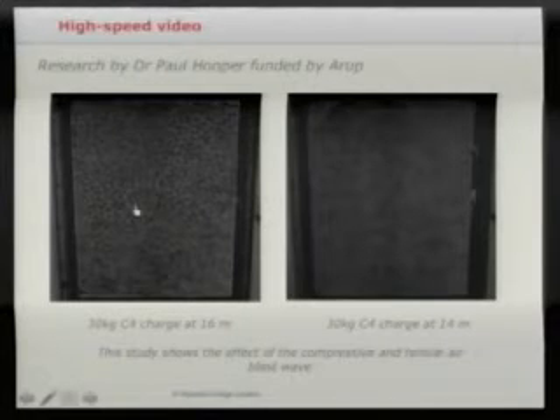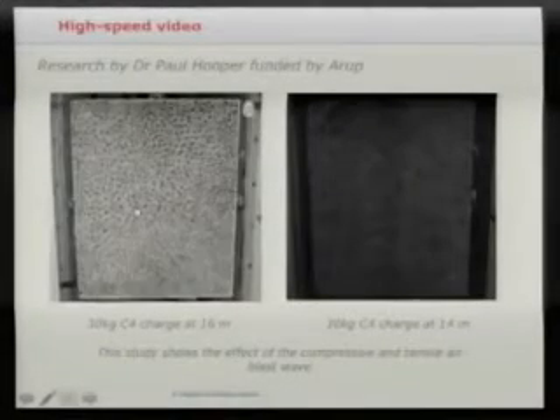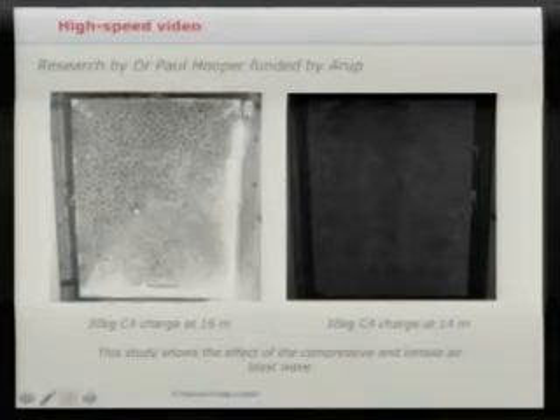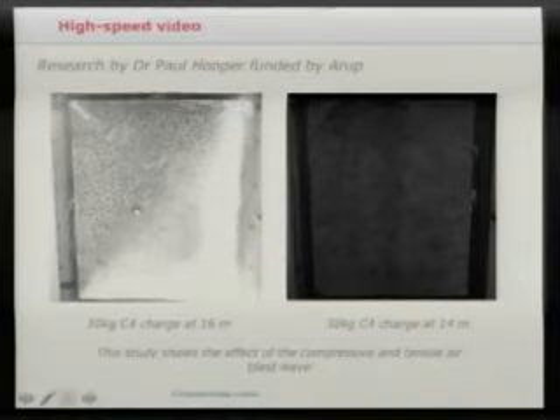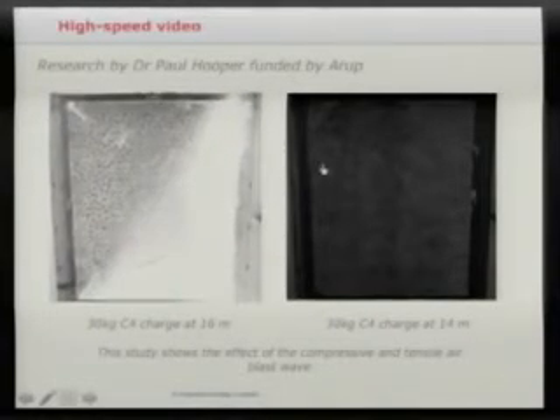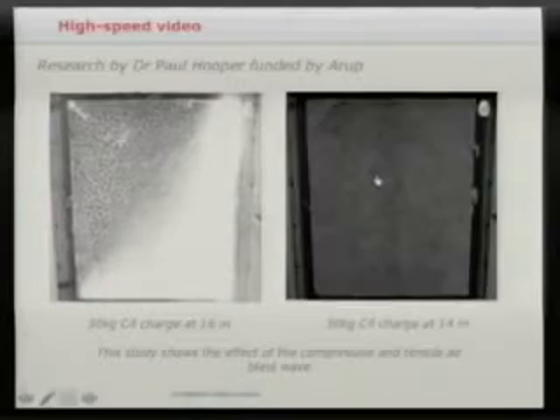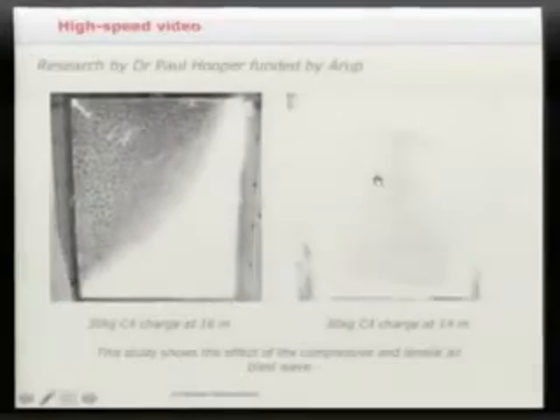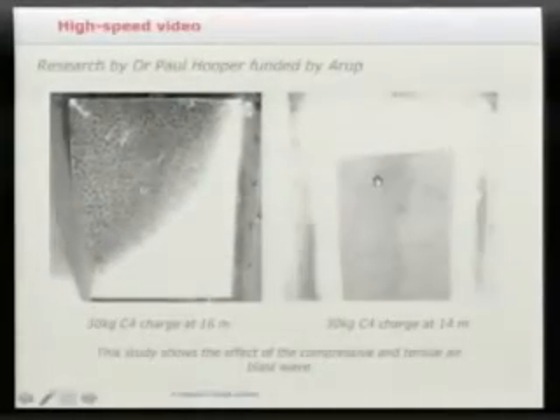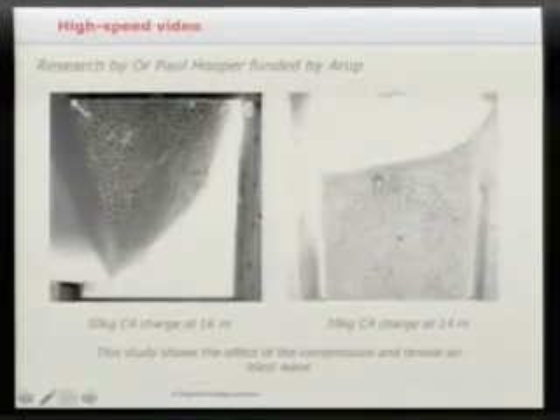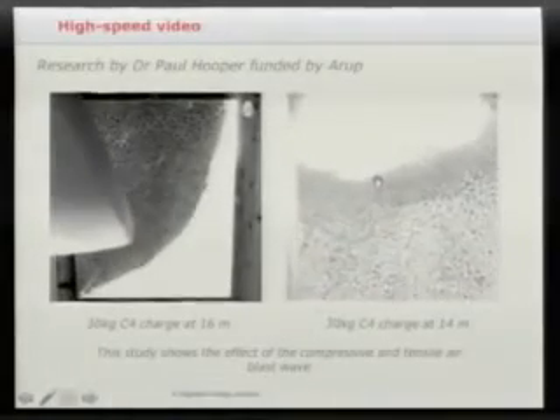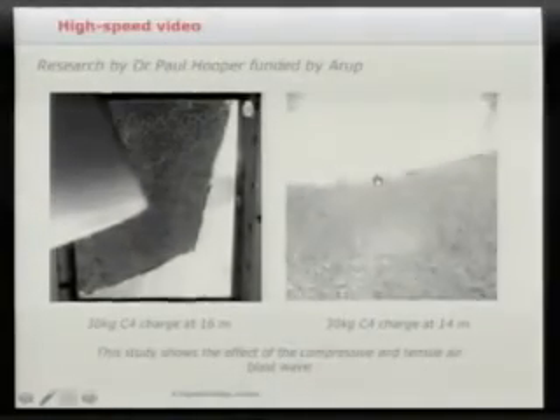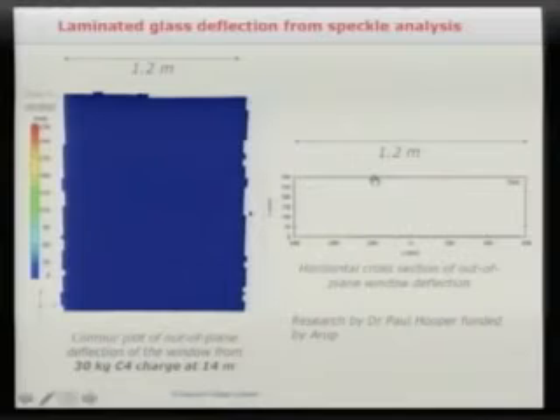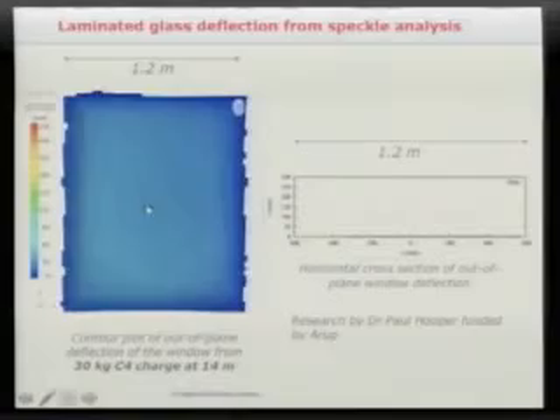So if I play this one first, you can see the flash of light, and then the whole laminated glass sheet gets pushed in and pulled out. If the charge is slightly closer, the effect of that is that, in this case, the laminated glass sheet gets pushed into the cubicle. Now, what we then do with the high-speed cameras is track all those speckles, and we can then build up a deformation map from that speckle data.